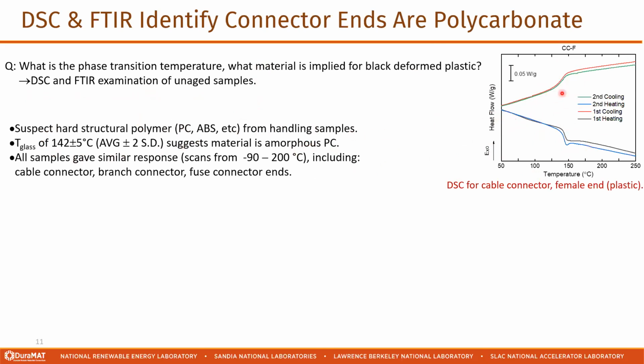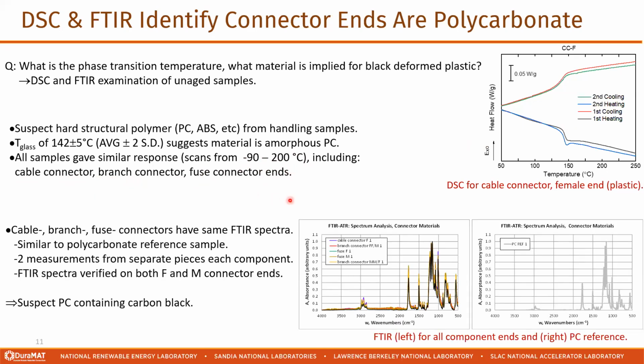This is an amorphous material, and this is characteristic. You'd find this like in polycarbonate. And all the samples that we looked at, measuring from 90 below to 200 above, gave a similar response. We looked at the cable connectors, the branch connectors, and the ends of the fuses, which are all this black plastic material. So to compare to that, we also did the FTIR characterization.